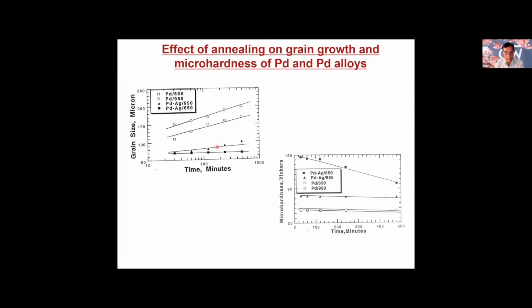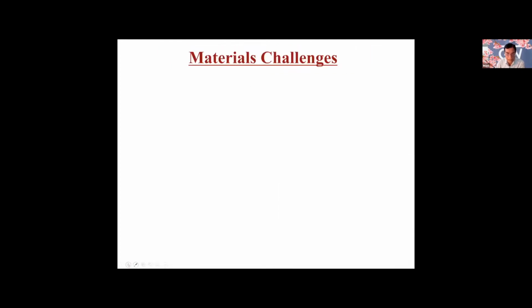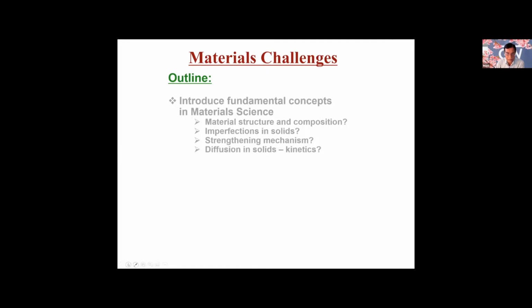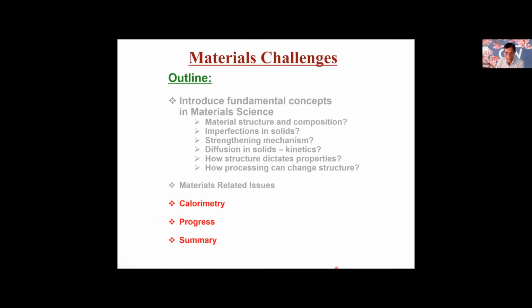You can see that the higher temperature will give you a larger grain size, and this is for 650 here. And again, just to relate to this one here, you can see that the microhardness changes as we change the grain size. So grain size plays an important role in two ways. The material's mechanical properties change, and another is that diffusion will be faster in a smaller grain size compared to a larger grain size. Looking further, just to show you some of the calorimetry work which was done, and then progress and the summary.